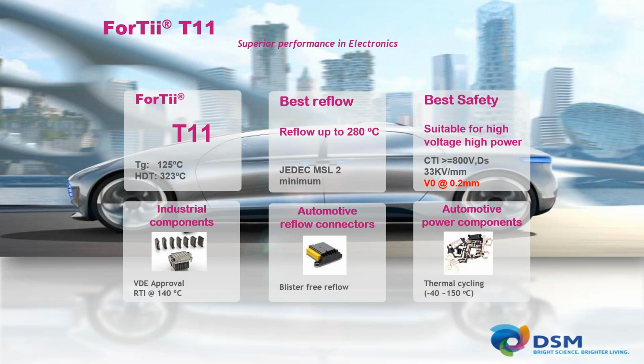The other one on lifetime that's also worth mentioning, maybe that's also what is meant, is the RTI values of these materials. And that's then either electrical withstand, basically. The T11 is RTI rated 140 degrees C for the electrical performance, and depending on the thickness of mechanics and mechanics with impact, it can be either 140 or 130. But also those are available throughout the yellow cards, basically. And if you detail the question a bit more specific, we can come back to you with the exact data on what the lifetime is at a certain temperature.